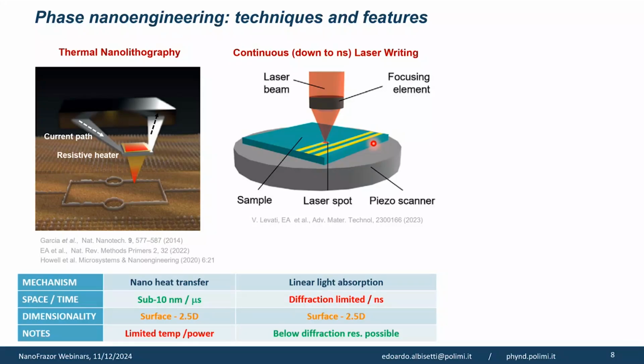And so the technique is really efficient if the material absorbs UV light efficiently. On the other hand, if the material is transparent, you don't actually have almost any heating of the material. So in this case, the type of material is even more important to trigger the transition, coupled with the technique itself.